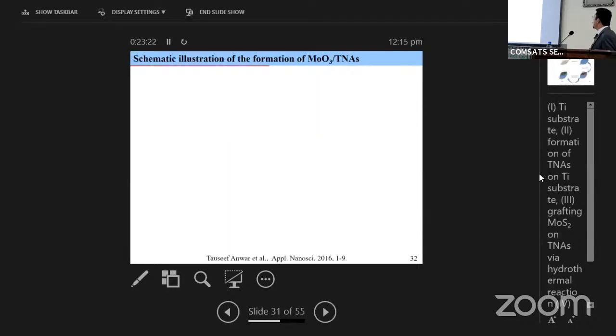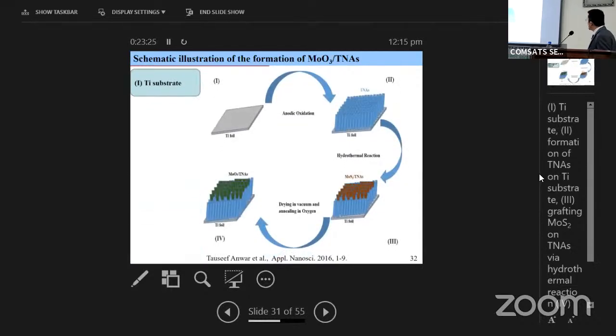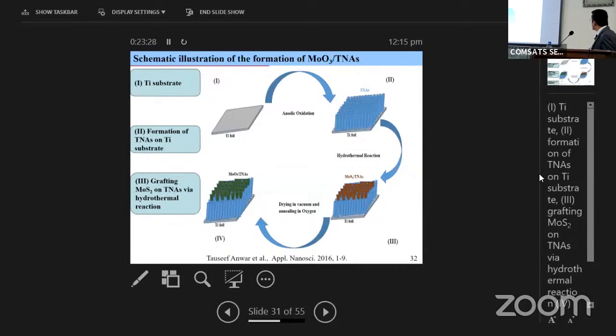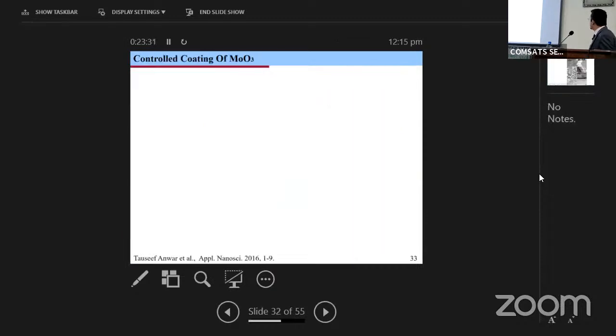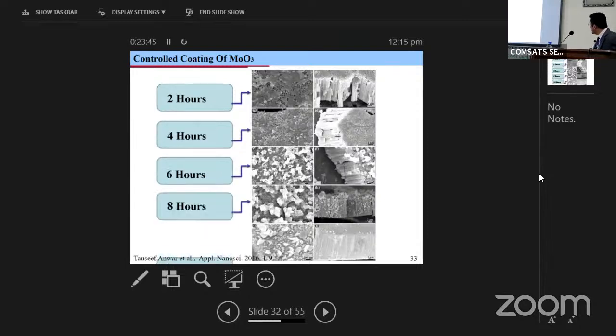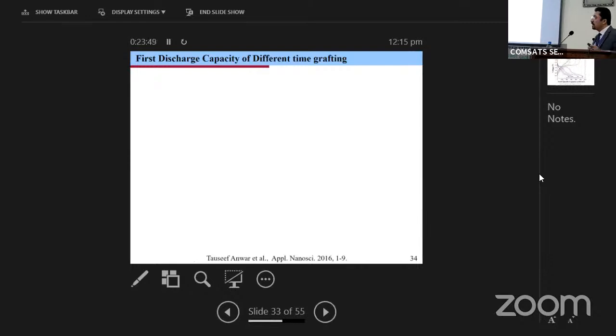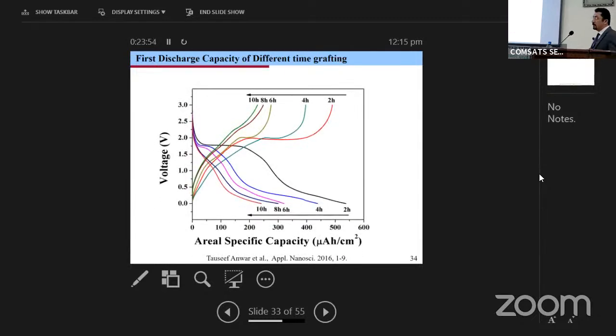In the second project, I tried to enhance its specific capacity. So I coated it with molybdenum trioxide, and that is optimization at different times, how long I coat this material on titanium dioxide nanotubes. I tried 2 hours, 4 hours, 6 hours, 8 hours, like this. I increased this time, and I did it. After this, at different times, I checked these nanotubes as anode material, and I found that 4 hours has very good capacity. So I selected 4 hours